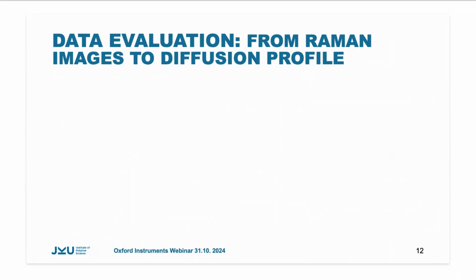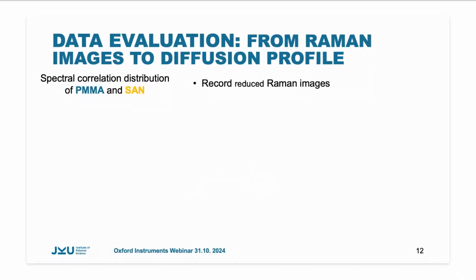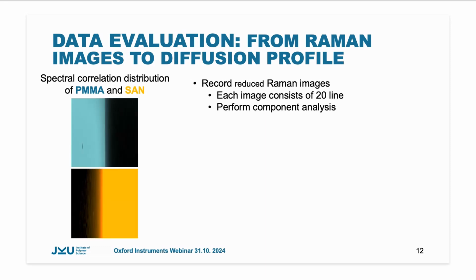How to get from a Raman image to a diffusion profile is not as straightforward as we thought in the beginning. We have the spectral correlation distribution of the PMMA SAN mixtures. We record what I call reduced Raman images, because we have a high number of spectra along the line, but only 20 lines are recorded. Then we perform the component analysis and we get the images for the mixing factors.